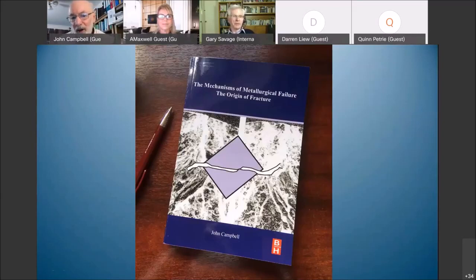So the fact that they are cracked has to be some other explanation. It's not due to stress. It's simply due to the fact the carbides precipitate either side of bifilms, and by accommodating these shape changes and volume changes, they prise open the bifilm, and the two sides of the bifilm move apart a little and reveal the crack.